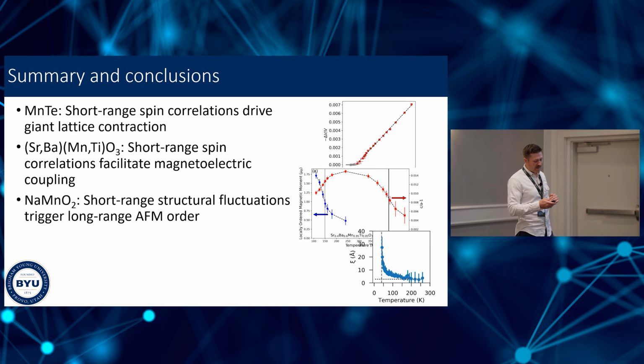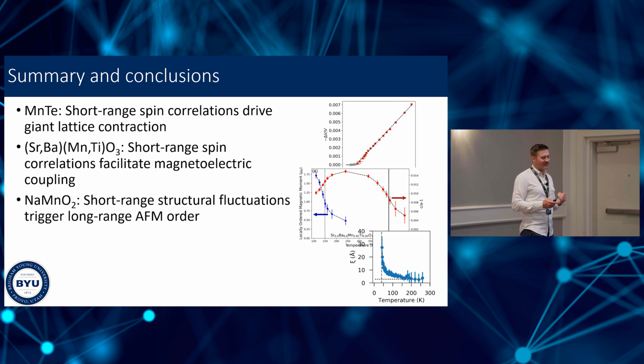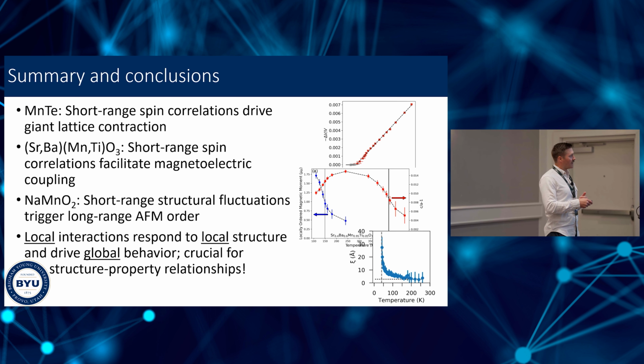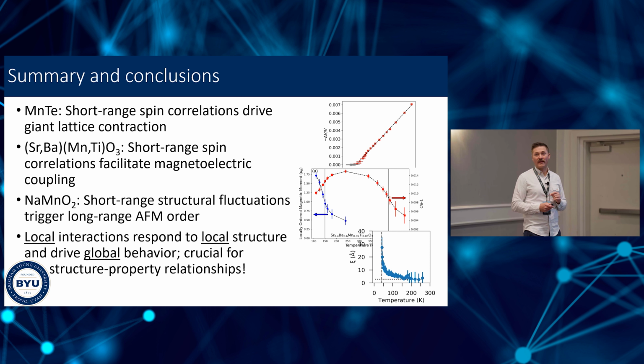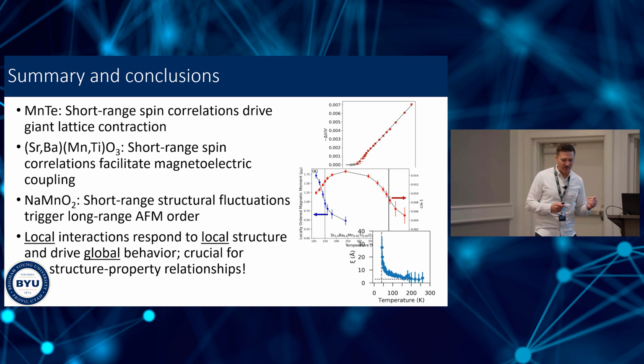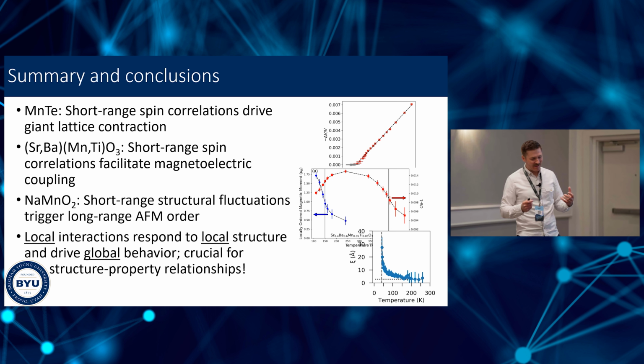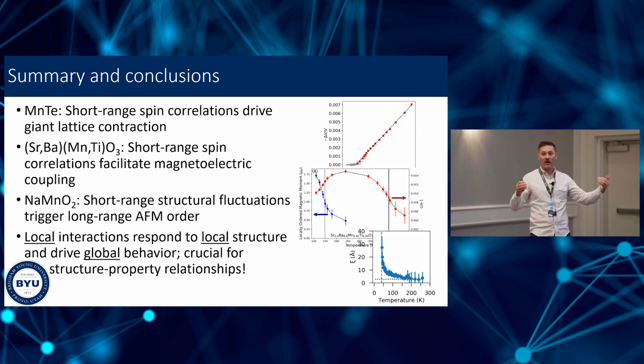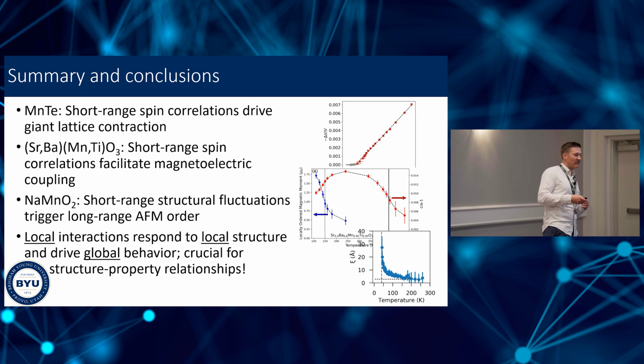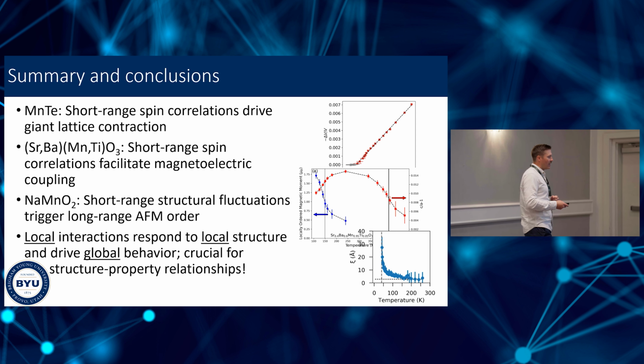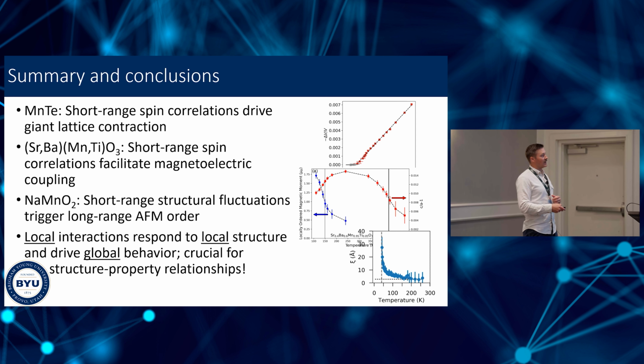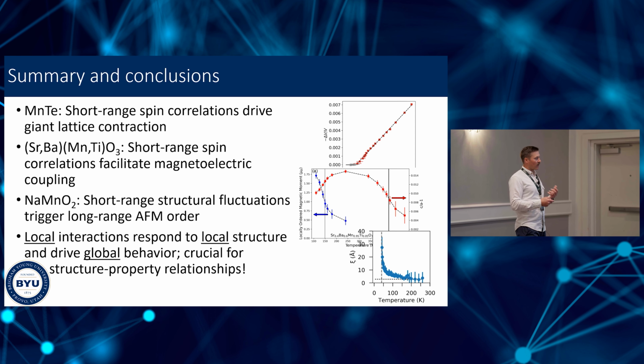So these 3 examples together, to me, demonstrate a point which is actually quite obvious, which is that local interactions respond to local structure. And yet, they can drive global behavior. So, in the end, this should not be so surprising that short-range magnetic correlations, even when they do not translate to long-range magnetic order, or short-range structural fluctuations that do not lock into a long-range crystallographic phase transition, are nevertheless able to influence electrons that are interacting through local interactions. And in the end, in these examples, and in many others that we've encountered, these local interactions are crucial for the global structure property relationships that we're interested in.